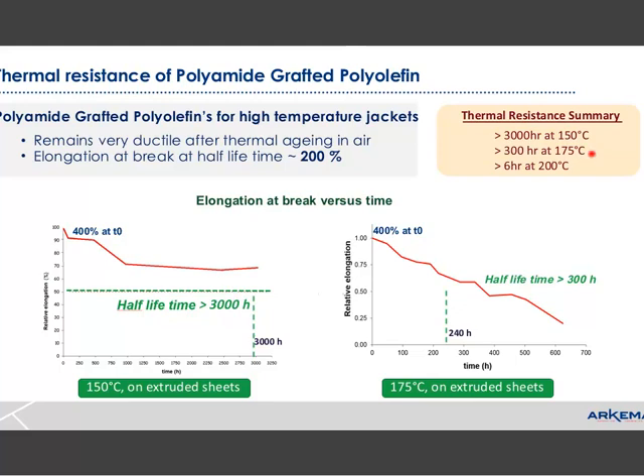Short-term exposure at 175 and 200 degrees C can also be handled with these resins, where you can see that 50% of the elongational properties are still retained after 300 hours at 175 degrees C.